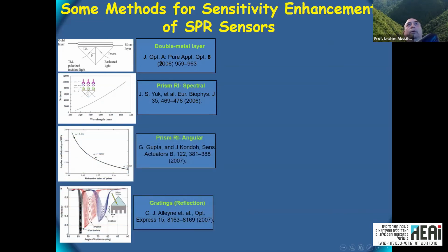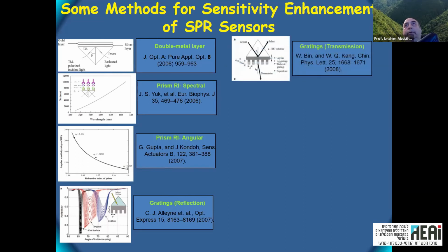For example, if you play with the metal, some metals give higher sensitivity. A combination of silver and gold was found to be the optimum. If you choose a prism with lower index, actually you get higher sensitivity. But there is a problem with each way. Each way you improve the sensitivity, there are other problems. I will not go over all of them because we don't have time. And some people use a nano grating on top of the metal and get enhancement by a factor of 7.